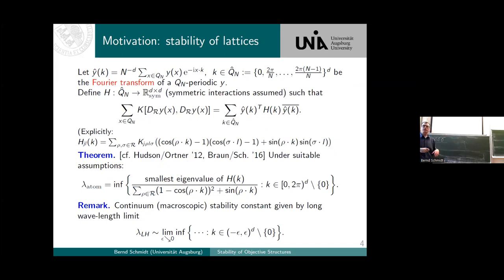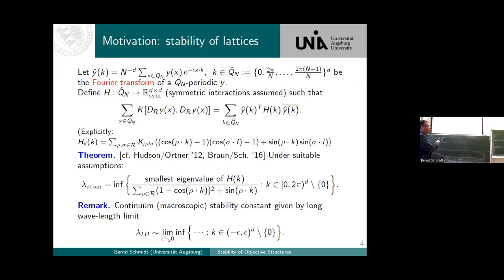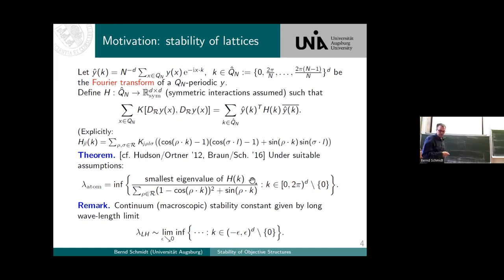As a remark, how does this compare to the usual criteria you know? If you go from discrete to continuum by a Cauchy-Born approximation, you have smooth perturbations where each atom follows individually. This corresponds to what happens at very low wave numbers. So the stability constant for the associated continuum problem only sees what happens at very small wave numbers, whereas the atomistic stability has to take into account all wave numbers. That's basic lattice stability.